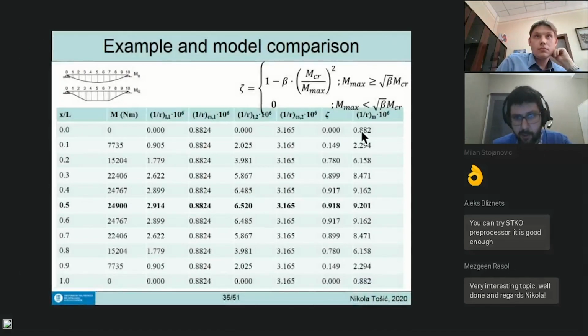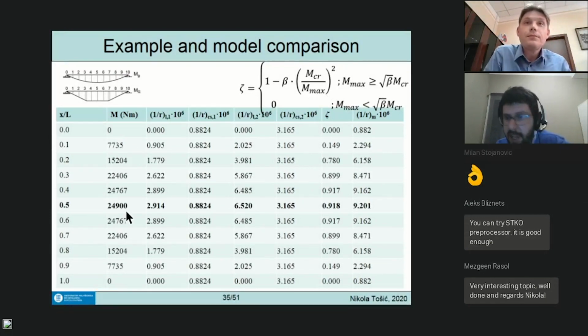Then I interpolate the curvatures using the zeta distribution coefficient. Here, M max is going to be this M. If I had a higher load that was applied and removed, that would be the moment I would introduce here, but it's not, so I have these moments going here. For beta, I used 0.5 because I'm calculating the final deflection.